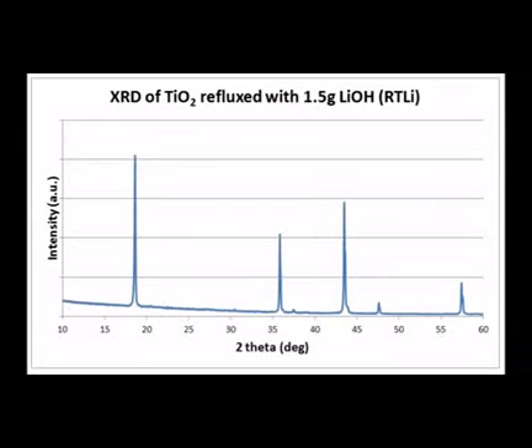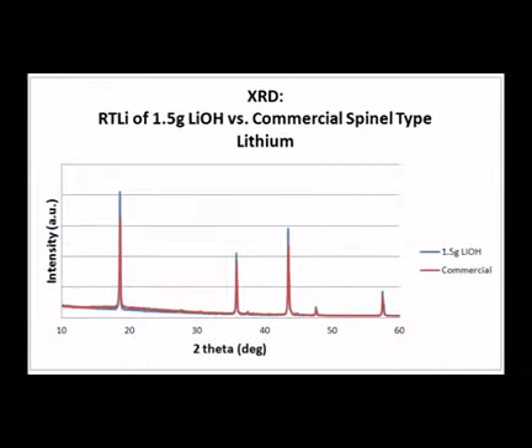Here we have an XRD graph showing the titania after being refluxed with 1.5 grams of lithium hydroxide. After calcination of the sample refluxed with lithium hydroxide, it leads to a pure phase lithium titanate. This XRD graph shows a comparison of commercial spinel-type lithium titanate with our sample. As we can see, our sample is a very good match to the commercial spinel-type lithium titanate.